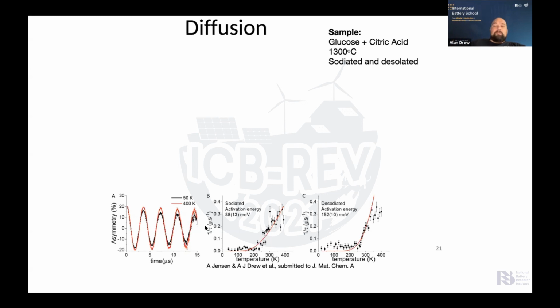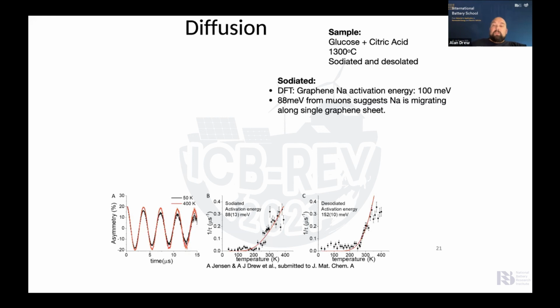And as you can see here, we've plotted diffusion as a function of temperature. And we can see that for a fully sodiated sample, we have an activation energy of about 88 millielectron volts, 90 millielectron volts. And for a fully desodiated sample, where there is still sodium, because it gets stuck, we have a much higher activation energy of 152 millielectron volts. Okay, if we look at sodiated, the DFT graph says it should be roughly 100 millielectron volt activation energy, but we see 88, which is pretty good.